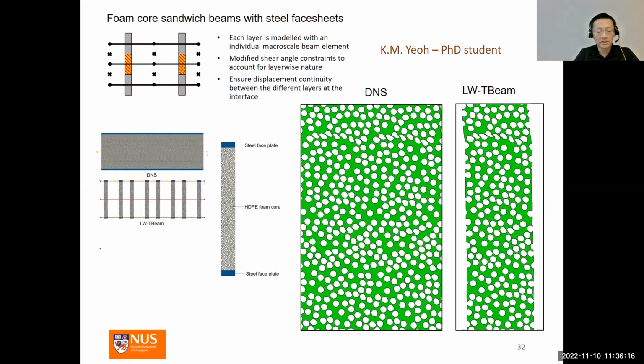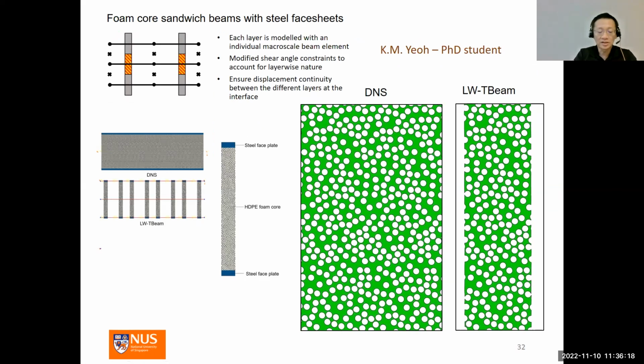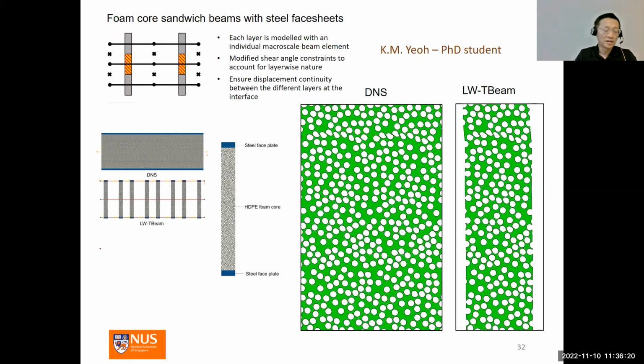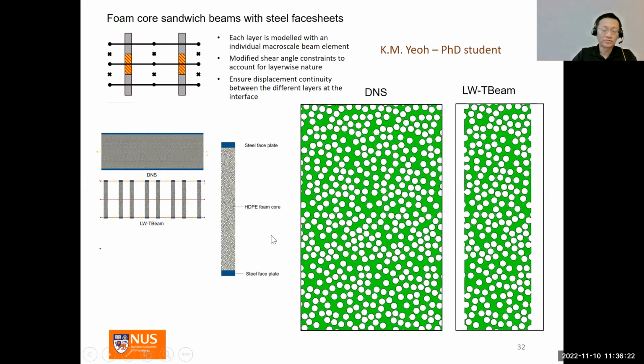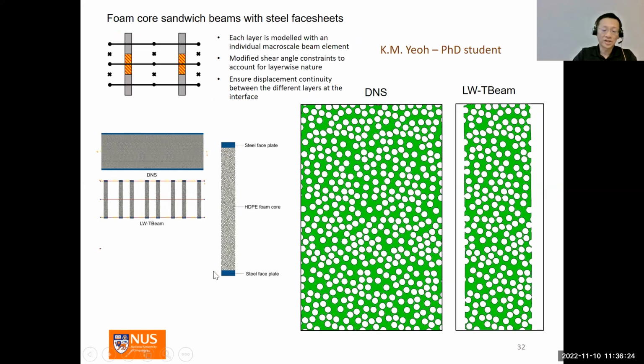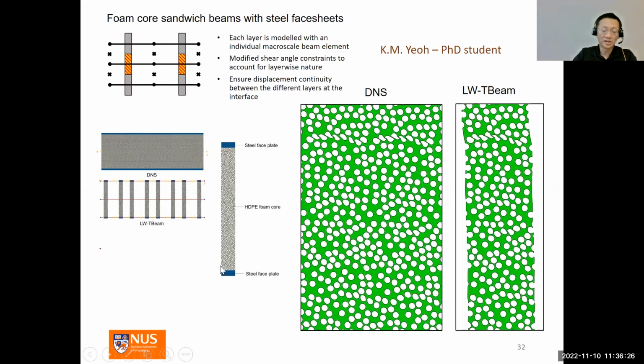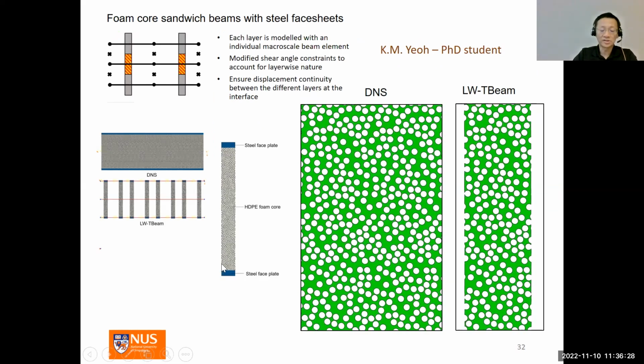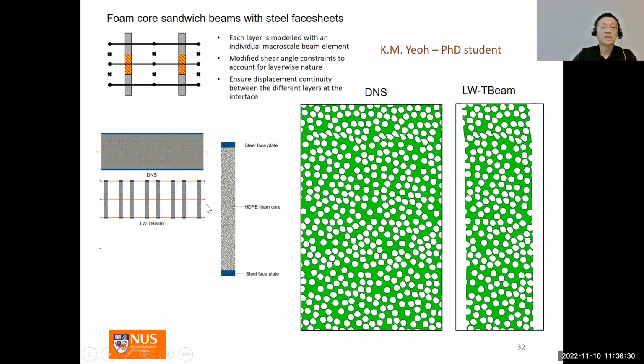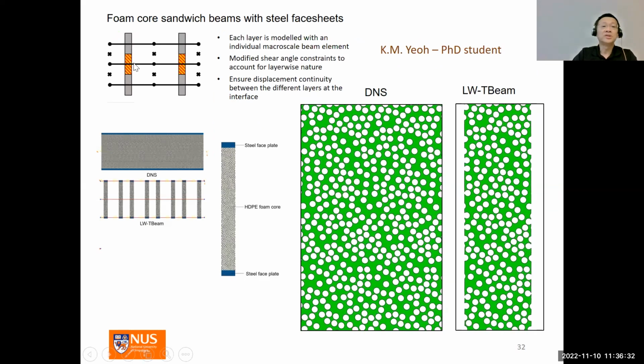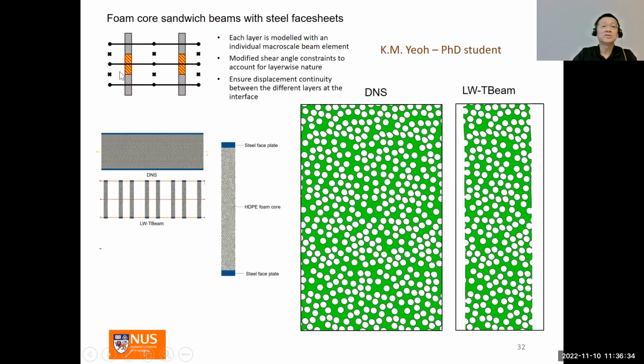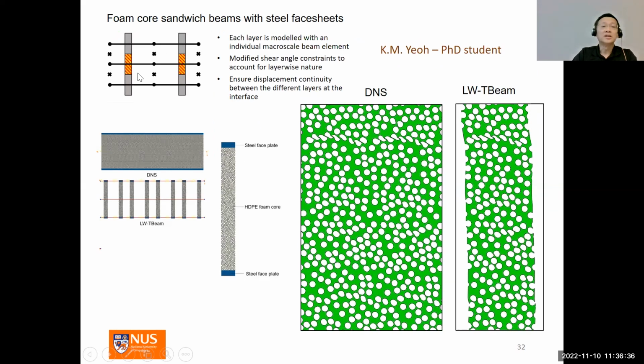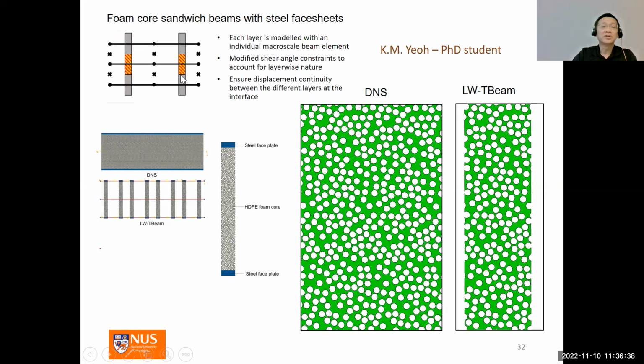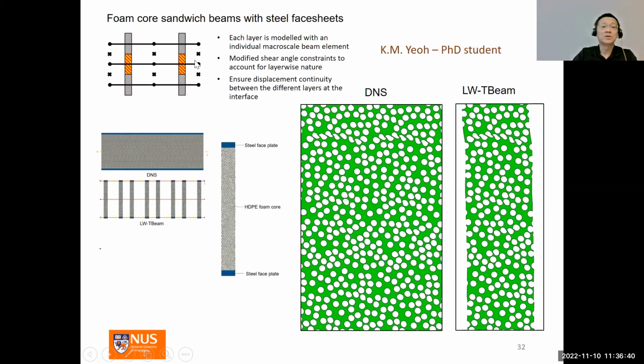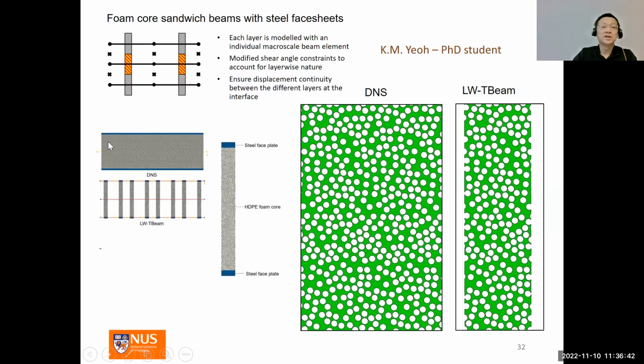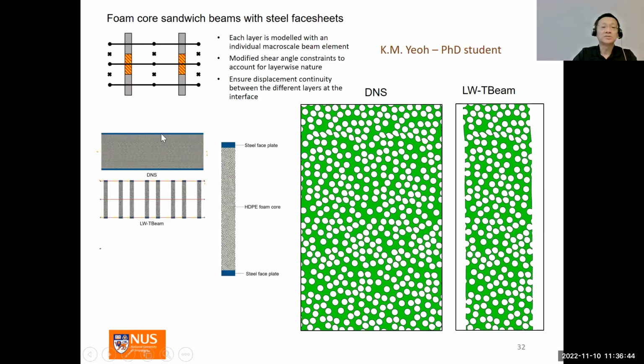In this slide, we applied the direct FE2 to model a foam core sandwich beam under bending using layer-wise Timoshenko beam elements. Here we have three beam elements, and the middle one is actually represented with foam core. So this is the DNS, a direct numerical solution model.